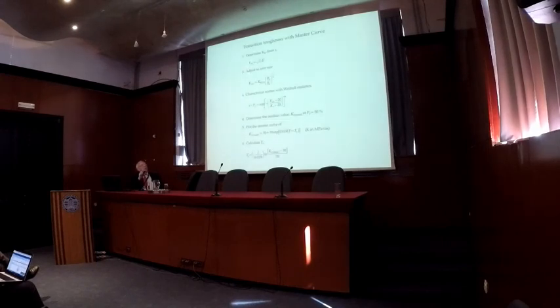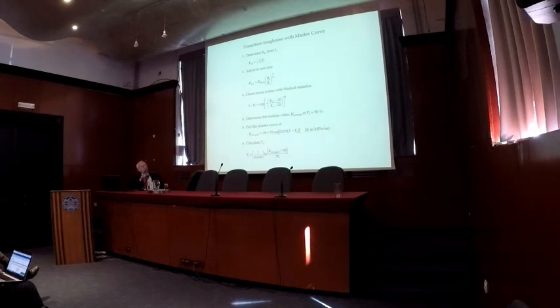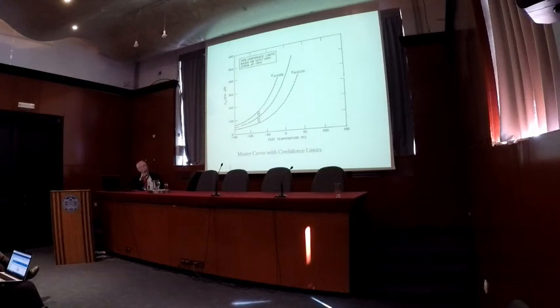So what was developed for this was Weibull statistics. And statistically, this was analyzed and the concept then of a master curve developed by Kim Wallen was the thing that was used to calculate the behavior. With a master curve, you could, with about six specimens, develop a median value of toughness, and from that, using statistics, get a lower bound or an upper bound.